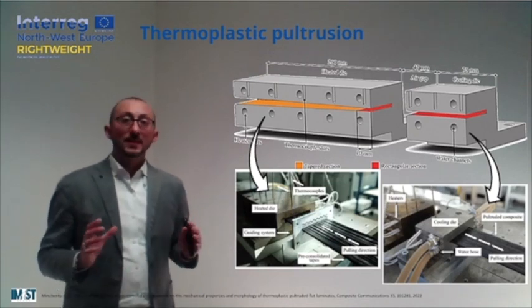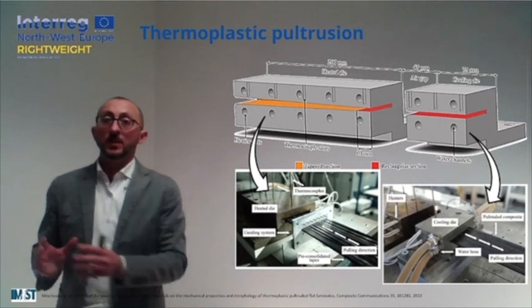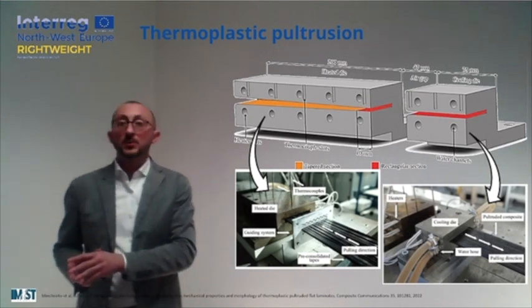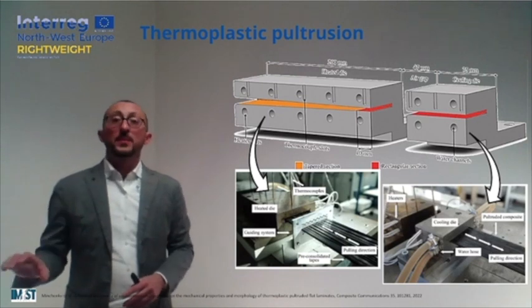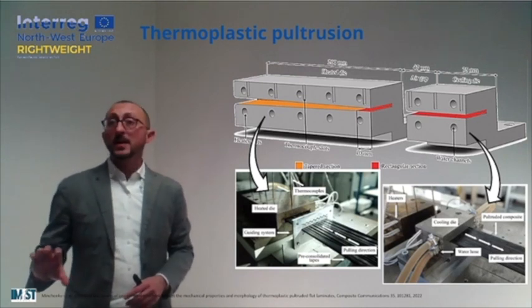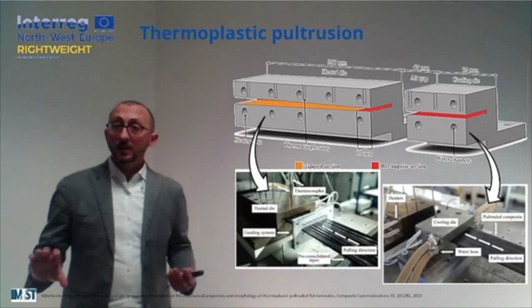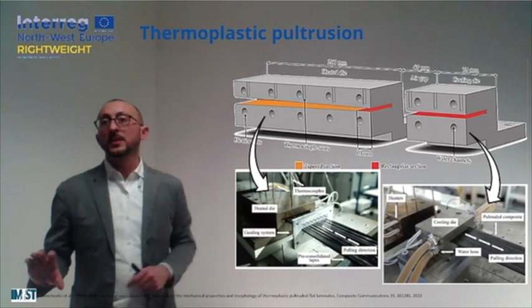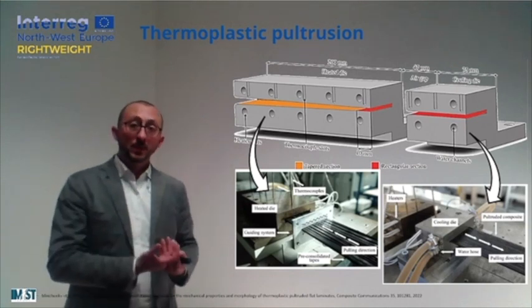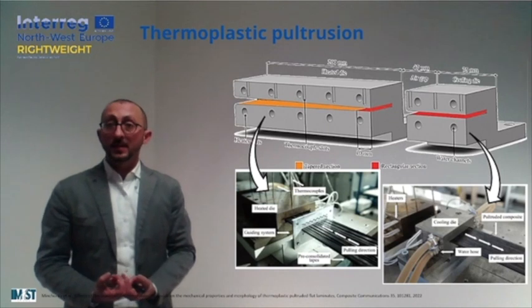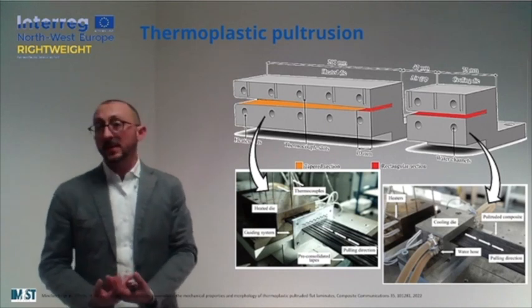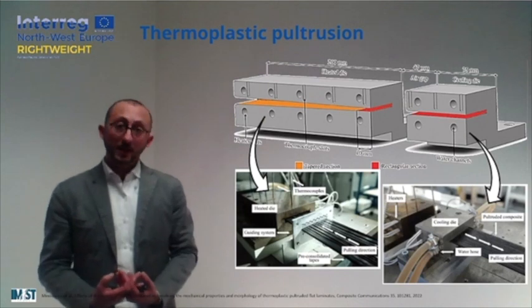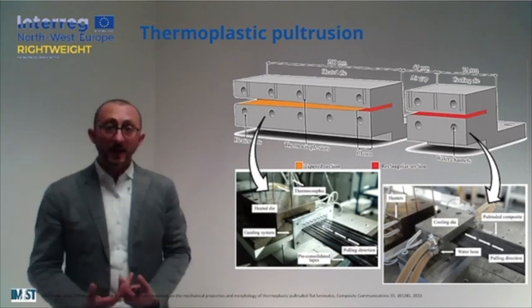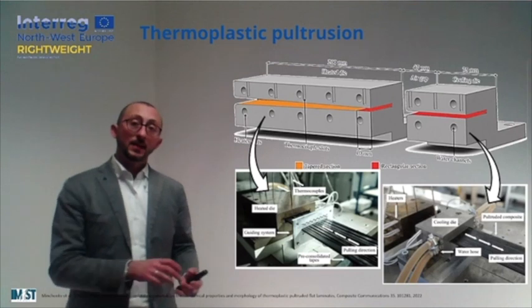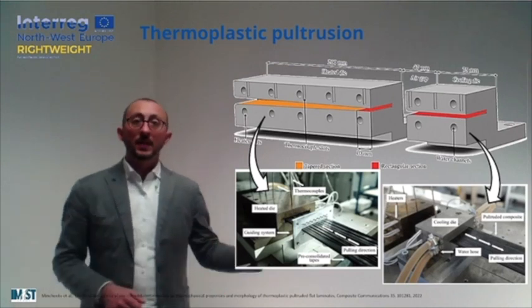So more or less it is exactly the opposite of the situation that we saw previously for thermoset pultrusion, where the preliminary portion of the die was cooled down in order to avoid a premature gelation of the resin, and then we went up with the temperature. Now, in order to soften our material, we have to heat up the thermoplastic resin, promote some kind of flow, some further wetting of the fibers, and then we can move on with the shaping of the material and the cooling.